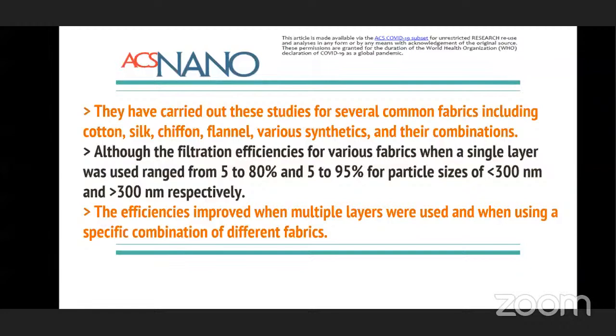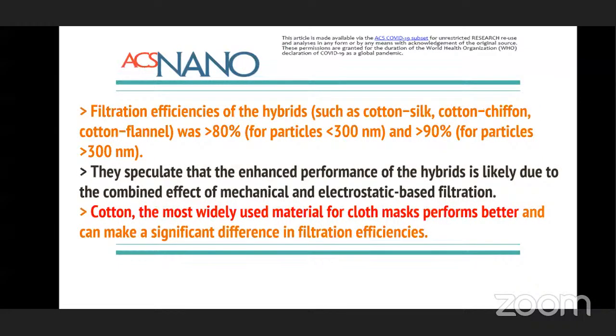The efficiency improved when multi-layers were used and when using a specific combination of different fabrics. So this is also an important observation, that multi-layer gives better efficiency. The filtration efficiency of the hybrids such as cotton silk, cotton chiffon, cotton flannel was more than 80% for particles less than 300 nanometer and more than 90% for particles more than 300 nanometer size. So this is also clear that efficiency increases if particle size increases.